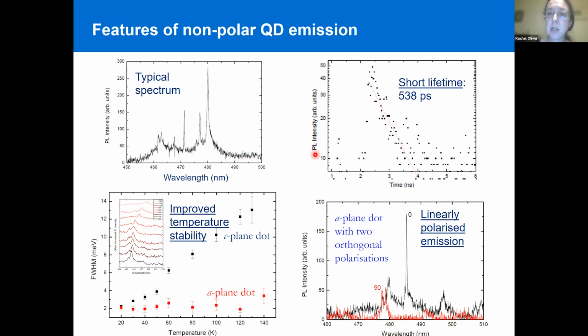However, if we look at the lifetime of that emission, it's now a great deal shorter. And that's the signature we were looking for of the reduction in the internal fields. The lifetimes here are about an order of magnitude faster than I was showing for similar wavelength emitting quantum dots on the polar C-plane, where the electric fields tend to dominate. So that's what we were expecting. That was the thing we were aiming to do by growing these non-polar quantum dots. So yay, we're there, great.